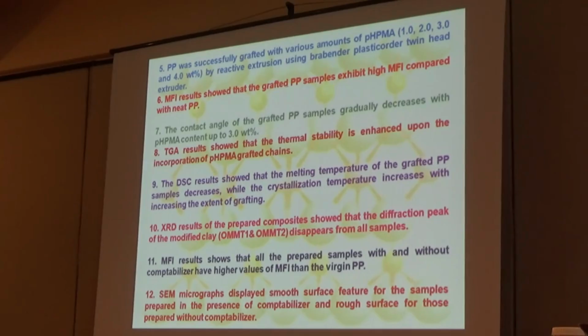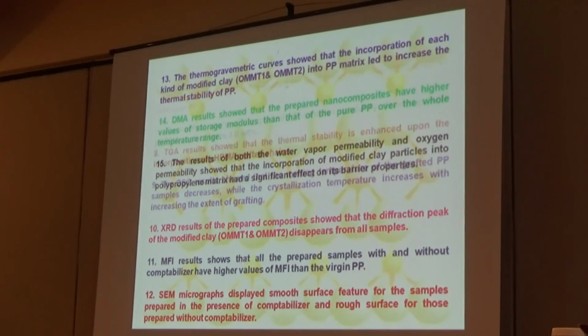XRD results of the prepared composite show that the diffraction peak of the modified clay disappears from all the samples. Melt flow index shows that all the prepared samples with and without compatibilizer have higher values of melt flow index than the virgin polypropylene. The scanning electron microscope micrograph displayed a smooth surface without fissures for all the samples in the presence of the compatibilizer, and a rough surface for those prepared without compatibilizer.